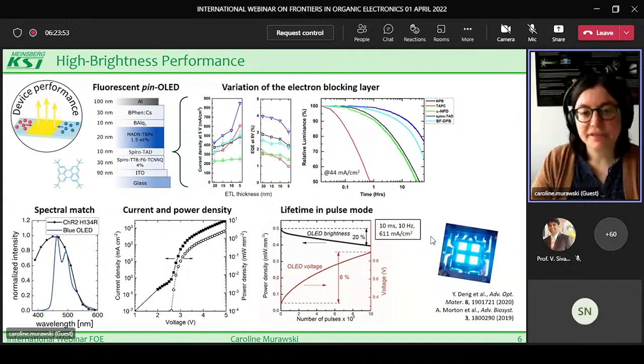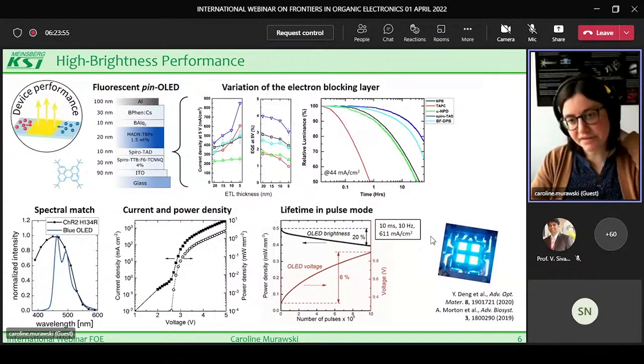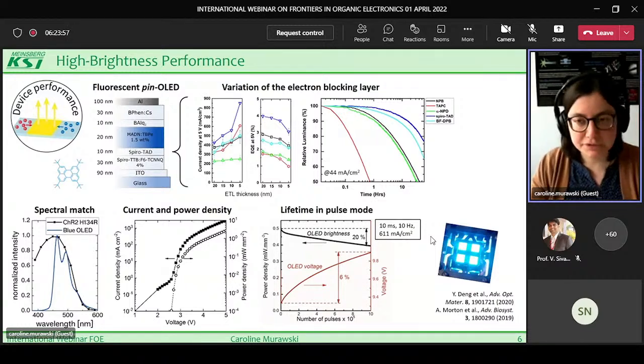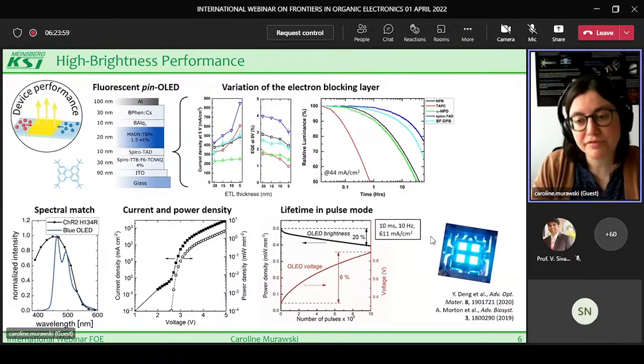We also studied the lifetime of these devices in a pulsed mode, because later we would mainly use a pulsed driving scheme in order to stimulate cells for some milliseconds. So in this case, we have 10 milliseconds and 10 hertz driving. And we drove the device at an initial brightness, or power density, of 0.5 milliwatt per square millimeter.